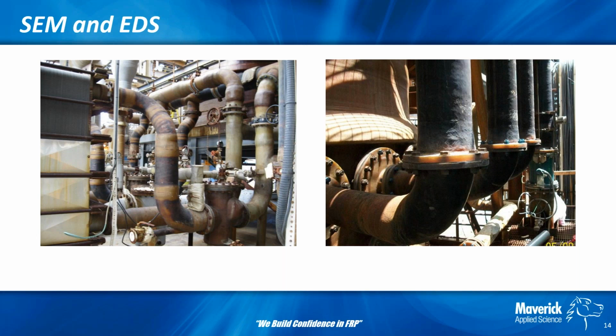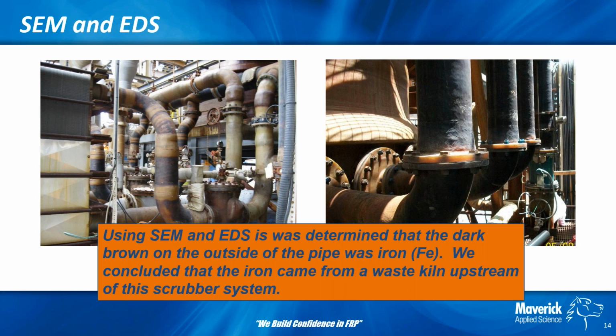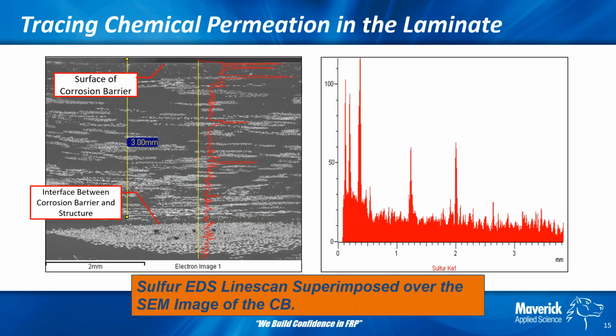And going back to the process operators, we found that there was a kiln, because this is a regenerative process, so kind of like a recycler. They had a hot kiln that was basically steel upstream of the scrubber, and this is just coming out of the quench unit within this scrubber system. It was basically carrying iron from the kiln, and actually it was collecting and depositing on the surface of the laminate here. So that was kind of an interesting find. We actually went back and confirmed that a second time, because it just didn't make sense the first time. So we thought, well, maybe something was an error, but in actuality, that iron is the dark discolorations you see here. So that's a little bit about that.